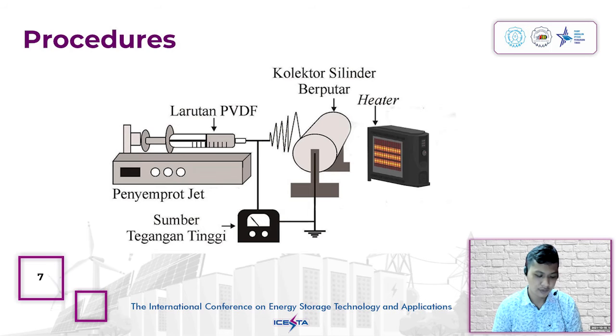Next is the electrospinning method. The PVDF SiO2 solution was inserted into the syringe. The tip of the needle was connected to the positive pole of a high voltage DC power source, while the ground of the high voltage DC power source was connected to a rotating cylindrical collector. The voltage was set at 15 kilovolts and the flow rate of the precursor was 1.6 milliliters per hour. The distance from the tip of the needle to the collector was 15 centimeters.